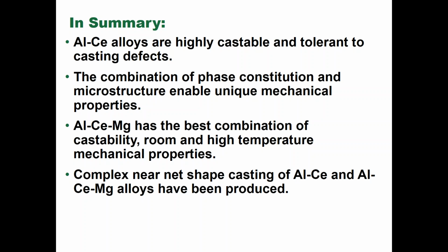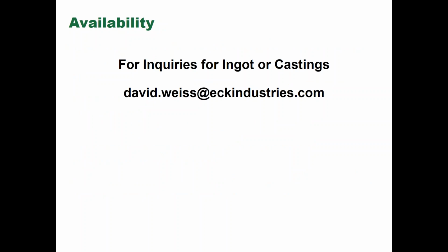The aluminum-cerium-magnesium alloys have the best combination of castability and room and high temperature mechanical properties, although we're continuing to work on improving those and looking at other alloying elements that will help. Complex near-net shape castings of aluminum-cerium and aluminum-cerium-magnesium alloys have been produced, and some of them are being evaluated for applications, in particular where operating environments are either steady state at higher temperatures or intermittently at very high temperatures. For any inquiries, that's my email address, and that's all I have this morning.